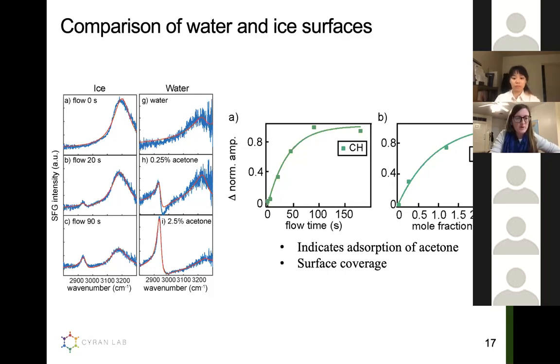So the first thing that I went through is I fit the data in order to extract some quantitative information. And here on the right-hand side, what I'm plotting is the change in the normalized amplitude versus the flow time. Or in the case of the water, I'm looking at the mole fraction. In the case of the ice, I was vapor depositing acetone on the surface, but for the water surface, how I did this was just make different concentrations of solutions containing acetone. And then the acetone is distributed in the solution, but you do get acetone also on the surface. What was cool is by fitting the data, we could look at how the change in the normalized amplitude changes as a function of the flow time or the mole fraction. So you can think about this as changing the concentration in this case.